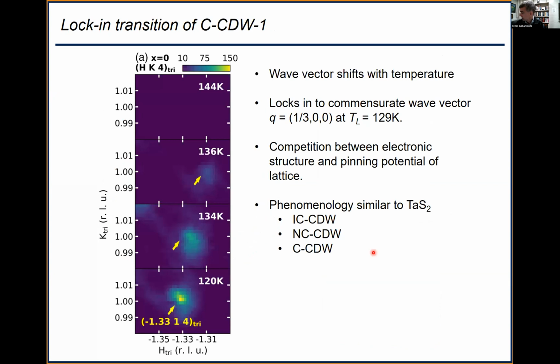Okay, so not all structural modulations are charge density waves. For example, BSCCO, if you know your high-Tc, has a supermodulation. It has nothing to do with CDWs. It just has to do with the fact that the bismuth oxide layers and the copper oxide layers have different periodicity. So when you put them together in a crystal, there's internal strain and it relieves itself by creating a buckling. So that's called an adaptive misfit effect. So if you want to prove this is a charge density wave, you need to do something else.